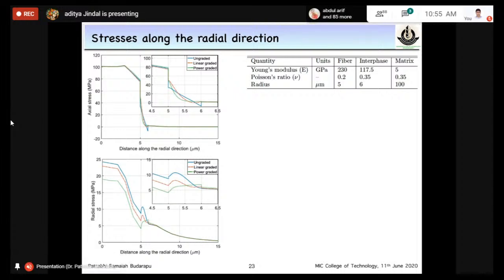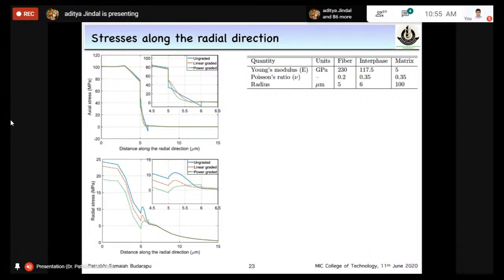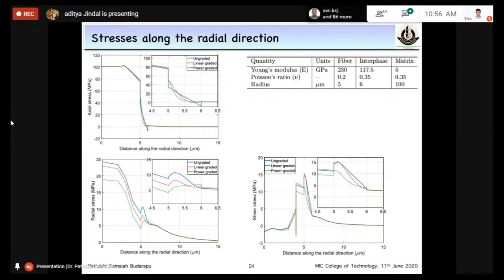Again, the power law plays a significant role — have a look at the zoomed picture. You can clearly see the power law is quite helpful in dropping the peak stresses significantly as compared to the linear law. This is the distribution of the radial stresses, and the distribution of the shear stresses is shown here, again showing the power law playing a role.